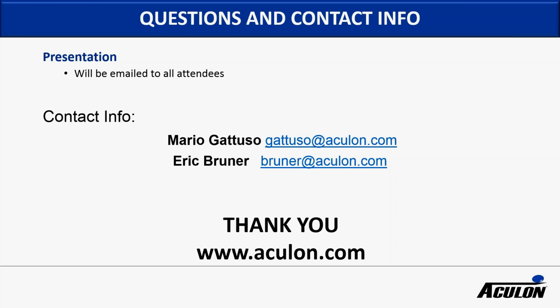Here's an interesting question. I don't know that we've looked at this, but do you have an aerophobic coating? In other words, we have an underwater application and we need to reduce the bubble adhesion of air to the surface. Yeah, we use hydrophilic coatings to do that for air displacement. If you use a hydrophilic coating on the surface, you should displace those air bubbles. So we can help you with that application if you want to send us details on your parts and product.